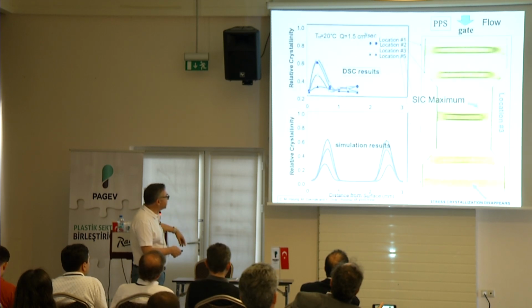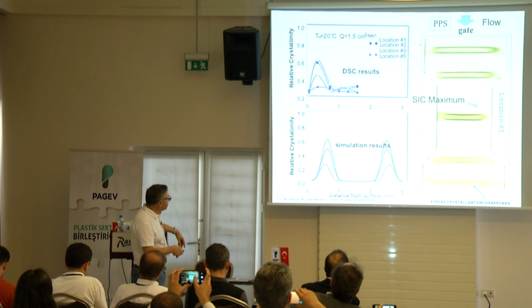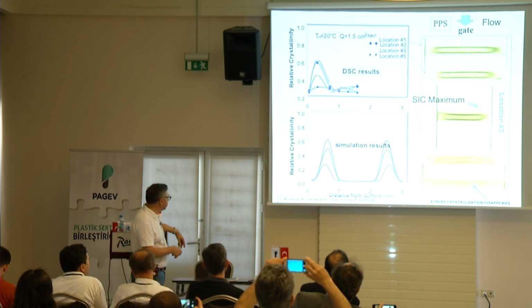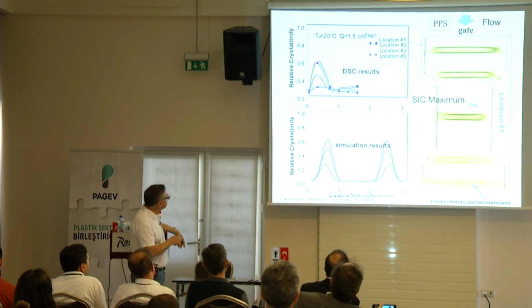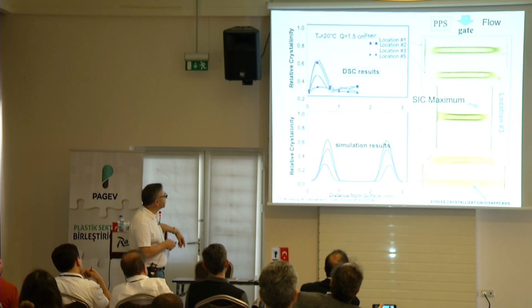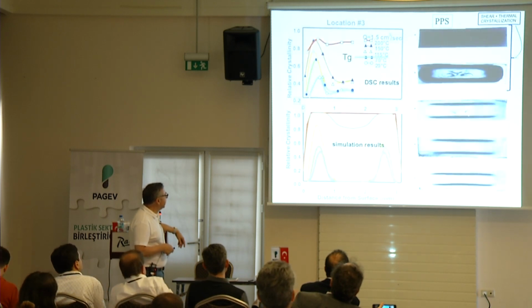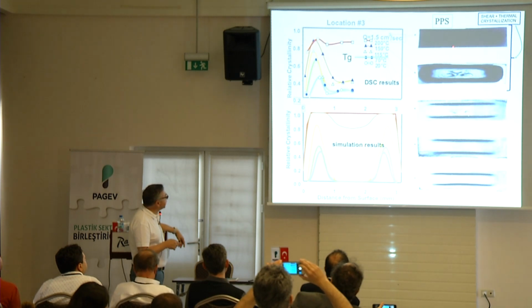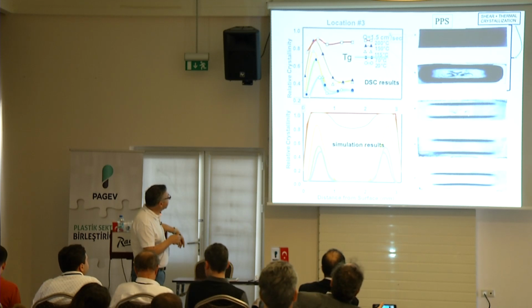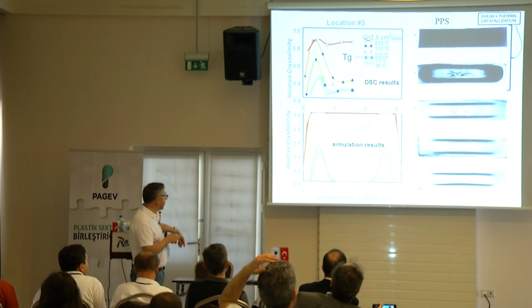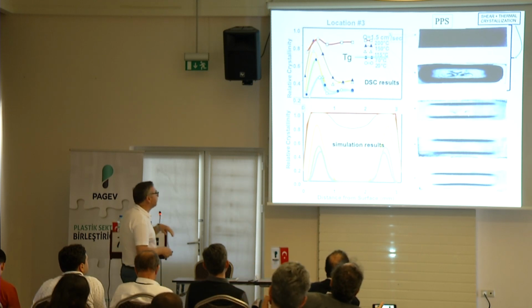Just verbally, we actually did the simulation, and this is work Shung and Jakub also worked on, that you can actually simulate this structure. So very similar simulations, the crystallinity evolution through the thickness direction in these materials. If you go to higher and higher temperatures, then thermal crystallization kicks in, especially here. Then the interior has a high crystallinity, while the skin still has a lower crystallinity. This is experimental. This is simulation work. All right.